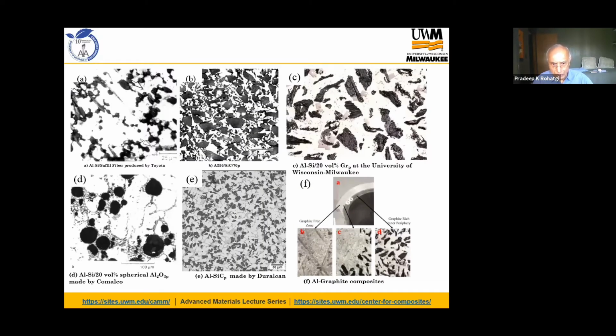I will show you some examples here of metal matrix composites, some microstructures, including some from components that have been synthesized. The first picture here is Saffil. Saffil is an aluminosilicate fiber. This dark Saffil fiber is embedded in the matrix of aluminum by squeeze casting, and this has been used in Toyota diesel engines since 1985. The second microstructure shows 70% particulate silicon carbide, this dark silicon carbide embedded in aluminum. This is being used as heat sinks in all laptops, probably the laptop that you have in your lap right now. The other microstructure is where graphite particles are embedded in the matrix of aluminum. If you look at the phase diagram, there is no miscibility of carbon in aluminum. You should not have been able to produce this based on thermodynamics.